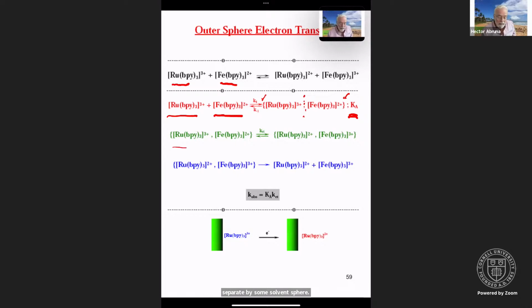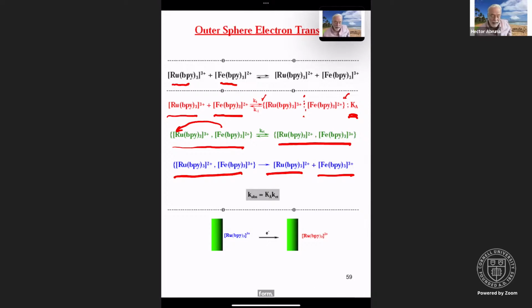Within this reaction partners, an electron can exchange. And so the electron goes from the iron-2 to ruthenium-3. So this guy is reducing that guy. This goes from iron-2 to iron-3. This goes from ruthenium-3 to ruthenium-2. Once you have that electron transfer having taken place, then these things dissociate and you end up with tris(bipyridyl)ruthenium-2, meaning the reduced form, and the oxidized form of the iron. And the k observed, the rate that you observe, will be equal to the rate of electron transfer, which is the rate determining step here, and this K association, or the association constant. At an electrode surface, you can think of it as having tris(bipyridine)ruthenium-3 and the electrode providing the electron to give you tris(bipyridine)ruthenium-2.